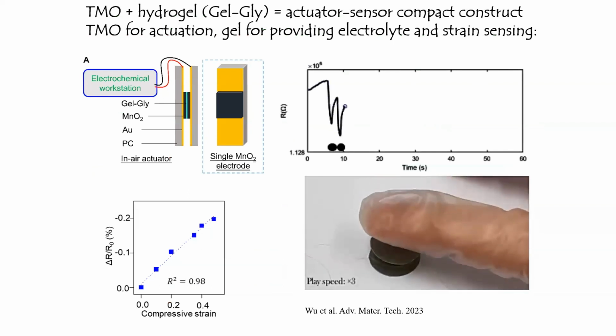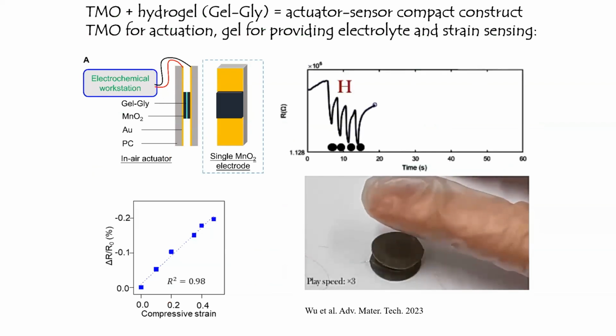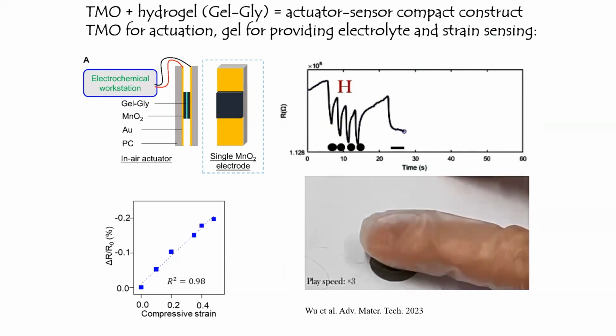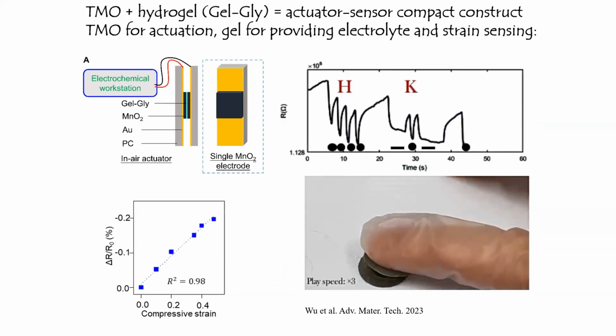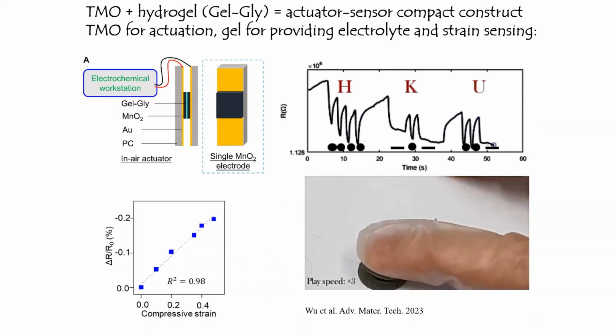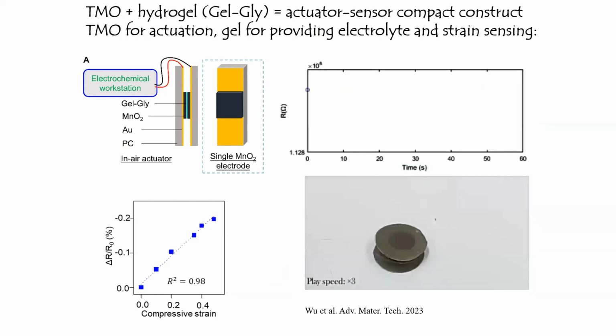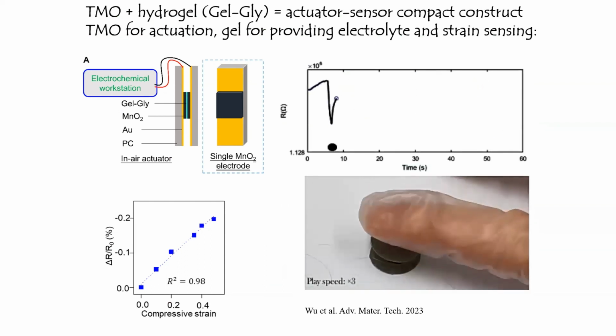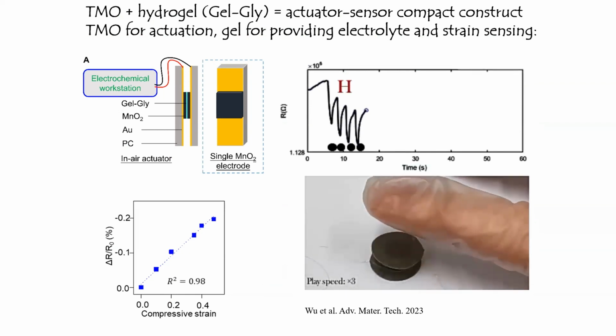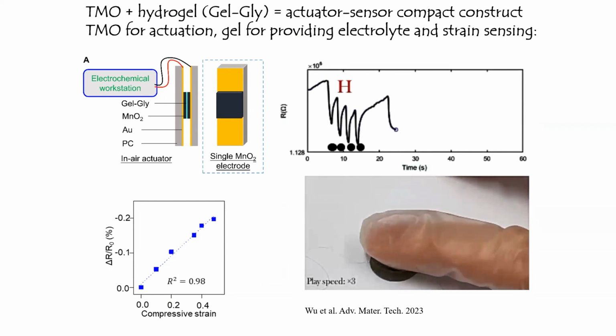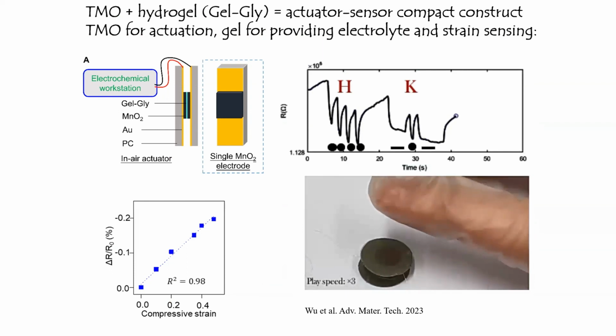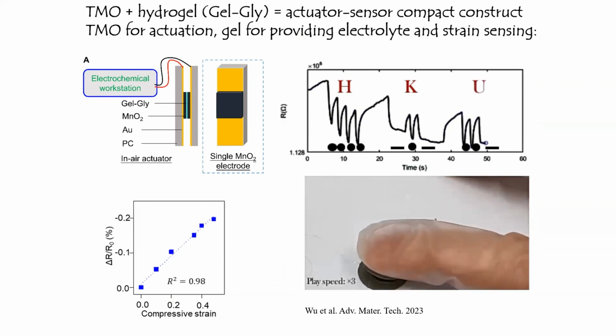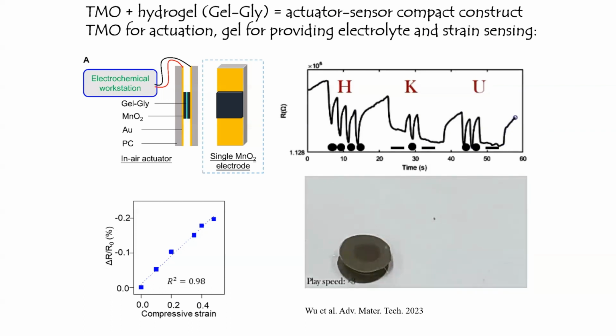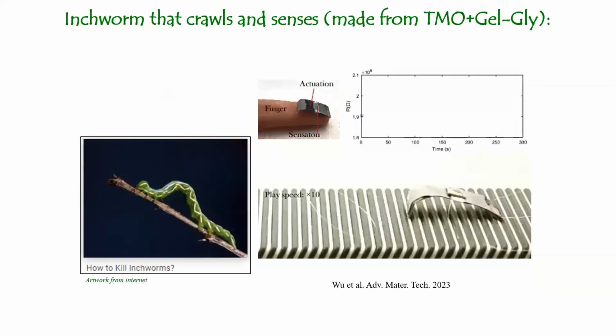So this is also a TMO with the hydrogel system, the same gelatin glycerol. So this is an actuator sensor compact construct. So the TMO is for actuation. The gel, as I said, is for providing as the electrolyte, but also this type of gel is also strain sensing. So if you squash the gel, the electrical resistance will change, and the change is pretty linear with respect to the strain. So this is a rather useful material to be used together with the TMO.